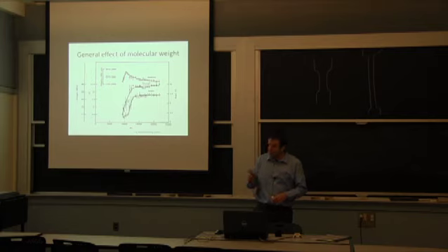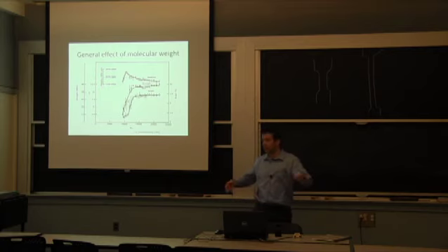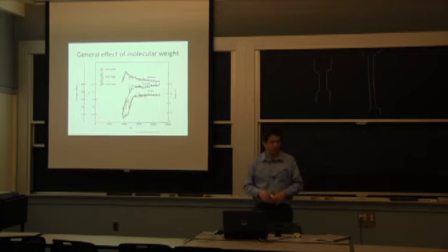If you wanted to simulate a creep failure, arguably you can do it by fatigue, because with the cyclic stress coming in and out, you get more fluctuation. You do get a lot more creep deformation under the same maximum load. It's a little bit hard to relate in terms of scaling the time as opposed to the cycles, but in terms of the process, there are a lot of people that have shown even a similar fracture surface by going under constant load and cyclic load for creep of polyethylene.